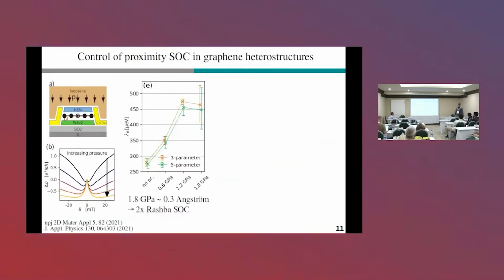And one way to do so is via external pressure. For example, in these experiments, it has been demonstrated that the proximity-induced spin-orbit coupling can be drastically enhanced by external pressure. So what happens? If you place such a heterostructure in a pressure cell, you will effectively reduce the van der Waals distance. Thereby, the coupling between the layers is enhanced, and also the proximity spin-orbit coupling is enhanced.